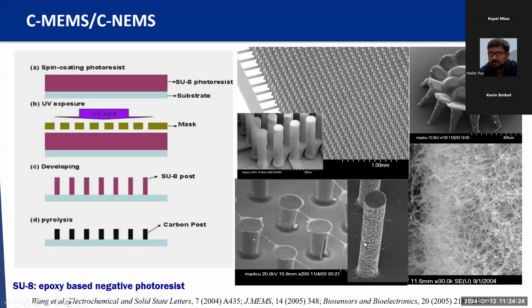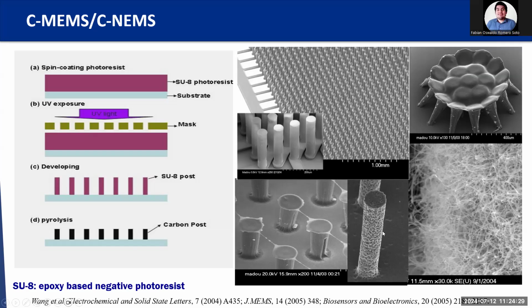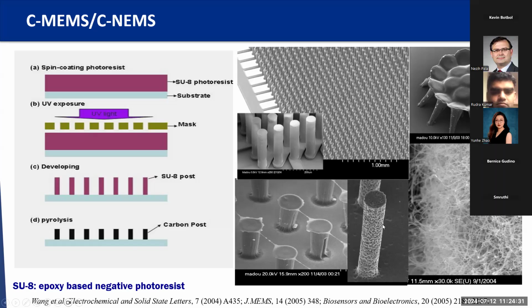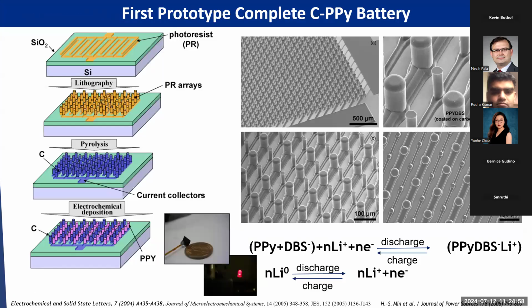For example, this picture shows porous carbon. Basically, during the degassing process, the carbonization process, gas gets out of this solid photoresist as it turns to carbon. Then you see all these porosities on the surface. And by adding catalyst, we can also deposit nanomaterials, one-dimensional or two-dimensional nanomaterials, on this solid glassy carbon post. So those are just typical carbon MEMS processes.